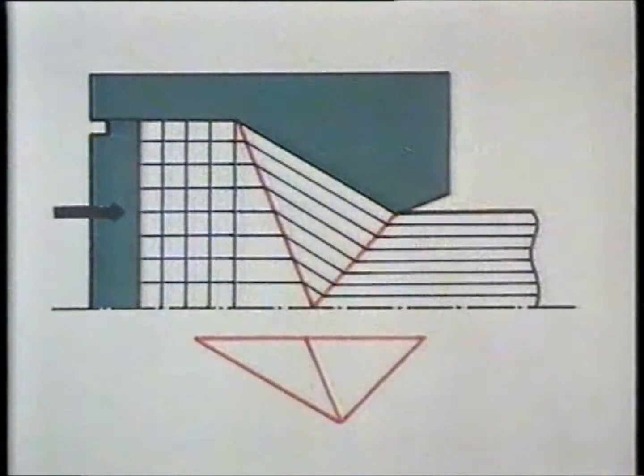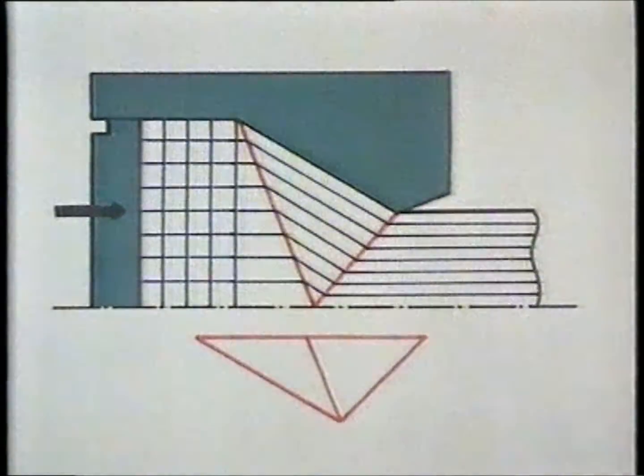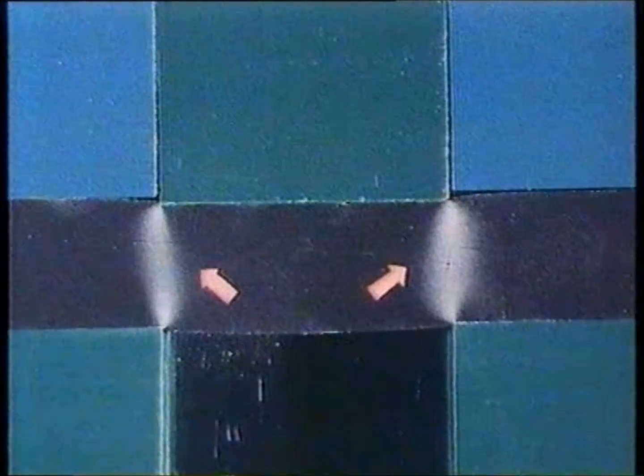In this way the deformation of the vertical lines can be drawn. Let us now look at another model material, slip line wax. This is a wax of a special composition which exhibits colour changes along lines of maximum shear stress. Here we simulate the blanking process in which two identical slip line fields appear on the surface due to the special properties of this wax.